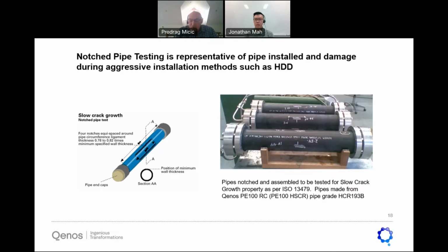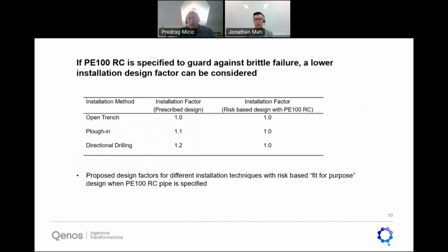But the test programs with notches deeper than the standard prescribed 20% of the pipe wall thickness demonstrated that the PE100 RC pipe with a notch depth of 30% considerably outperforms, in this relevant test, the standard PE100 pipe with a notch depth of 20%. So if PE100 RC is specified to guard against brittle failure as an integrity measure, a lower installation factor possibly can be considered. So while in a prescribed design, in this informative design factors, we can have for directional drilling 1.2, which gives us the wall thickness safety to guard against it.